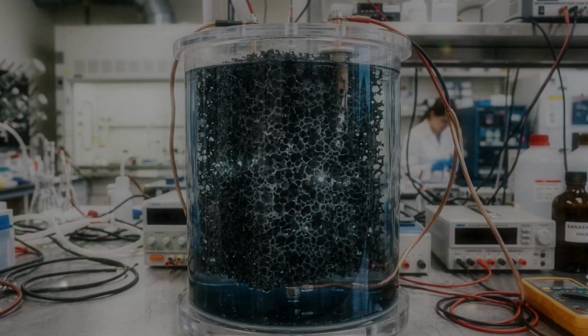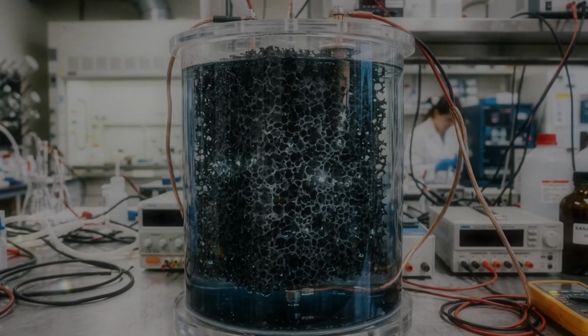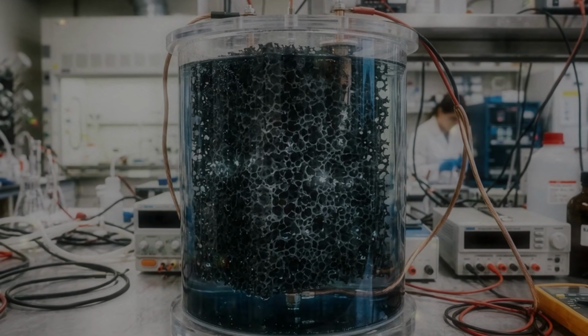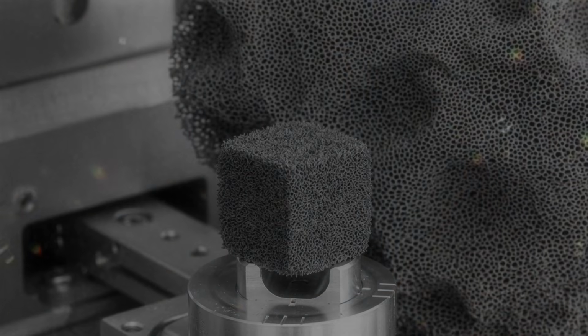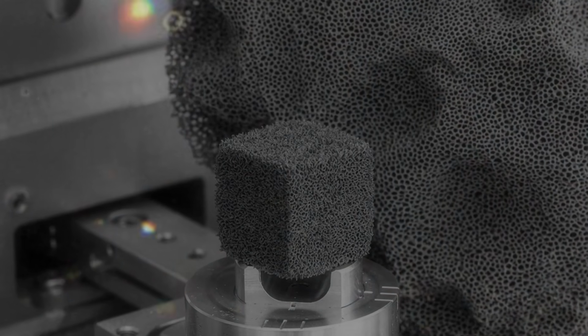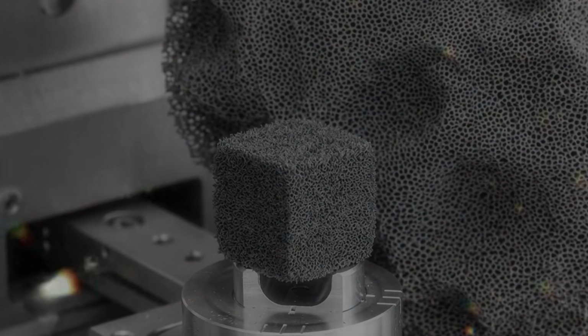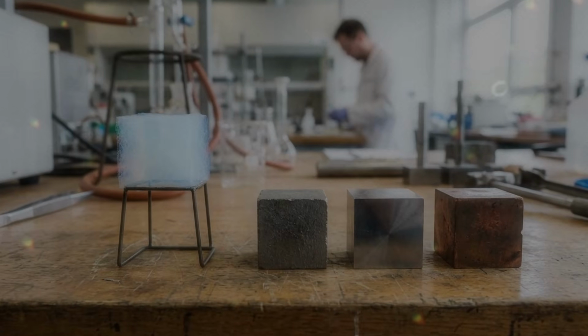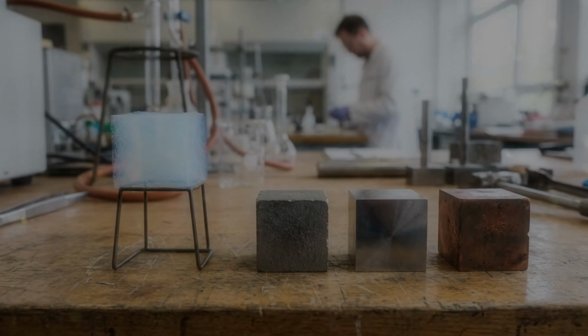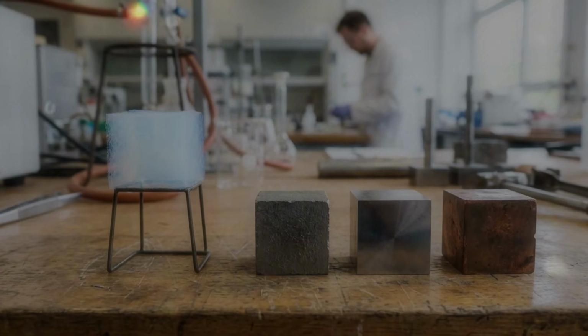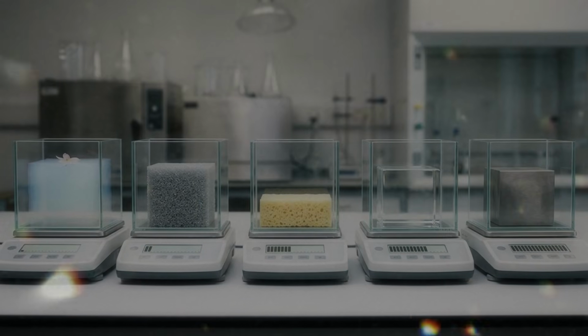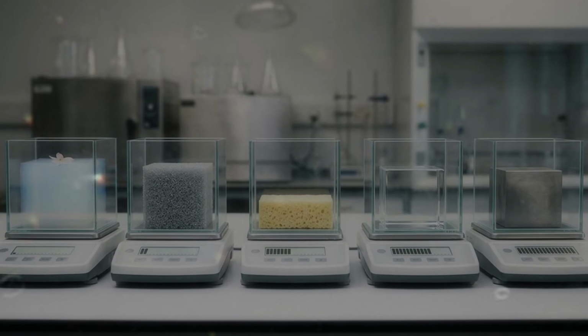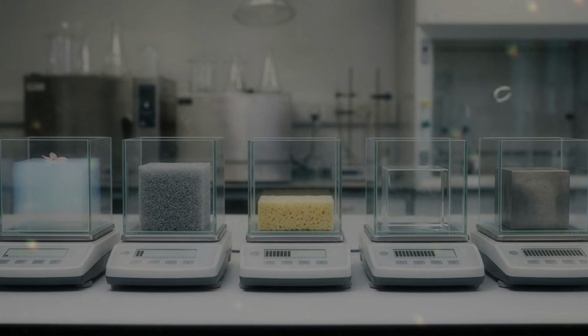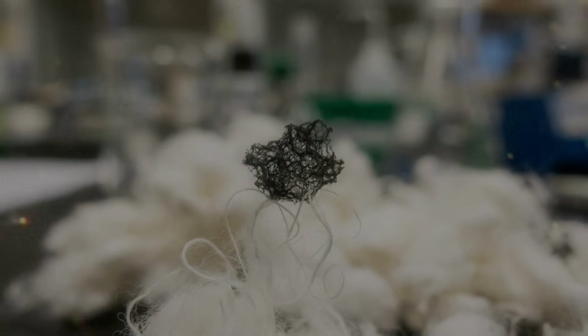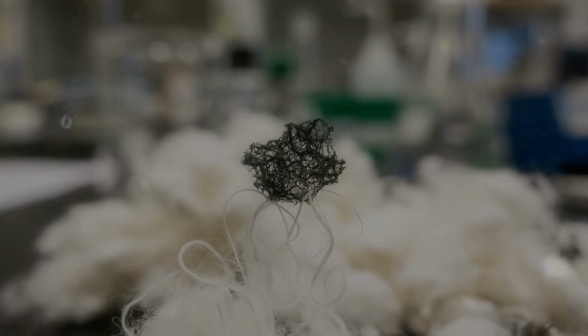Researchers can give graphene aerogels similar variations. One region may contain larger cells for compression. Another may contain smaller pores for strength. Layers can be arranged in different directions. Fibers can bridge weak boundaries. A gradient in density can prevent stress from concentrating suddenly. Instead of moving from a hard surface directly into a fragile interior, the structure changes gradually. Force spreads across a larger region.